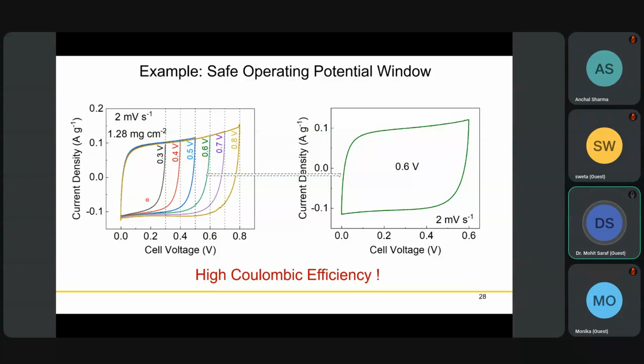Coulombic efficiency is just to see the discharge upon charge. Basically you can see it by the area also. If that is more or less 99%, then it is okay, so you can go further. So in 0.4 volt also, you get very high Coulombic efficiency, let's say 99% or 100%, it's okay. 0.5 volt, it's okay. 0.6 volt, it's okay.